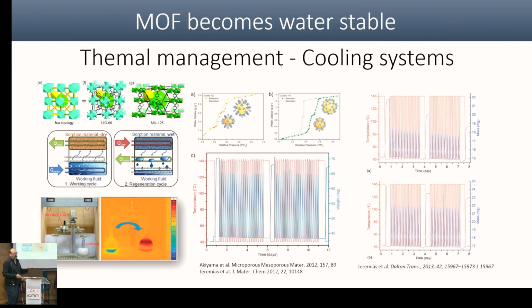We were using methanol, ethanol, ammonia to make a heat exchanger, to manage the temperature. And we were able to do this. But okay, we start using MOFs for heat control. That can be release of heat or decrease of temperature, cooling systems, using methanol or ethanol, because we all know that it was not stable to water. But they decided to measure, especially Janiak and Henninger, they started to make these kinds of experiments, and let's see how much energy we are exchanging. So we start with the cooling system and thermal management of this material.